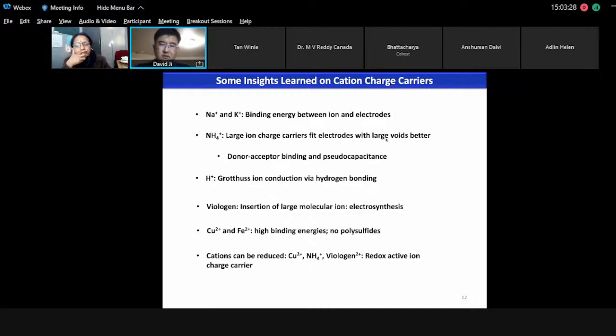Ammonium ion actually is quite interesting. It's non-metal. It's molecular. It has a lot of flavors to form chemical bonding in covalency and strong hydrogen bonding. Sometimes you could have pseudocapacitance simply just to study this material, this ion. But you have to worry about the hydrogen bonding flavors. If you use metal oxide, you can probably be very optimistic that you will see some kind of pseudocapacitance. Protons, I think, is a very promising technology because it has the potential to use Grotthuss conduction. But if you have too much lattice water, it's going to make your electrode quite heavy, right? That's a caveat.